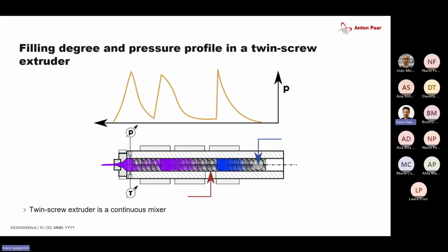What is not shown in the presentation, but is also quite interesting, is that our twin screw extruders come with an open clamshell design, which means you can open up the liner and look at where your material is placed alongside the screw. This is really helpful if you're still in the development phase, because you want to see what happens at what place. And just a side story, we recently had a trial with a customer that makes battery electrodes, where you have a small amount of PTFE, a binder which comes in small particles, and through high shear mixing you want to stretch these particles into long fibers to hold the active material of the electrode together to create a film.